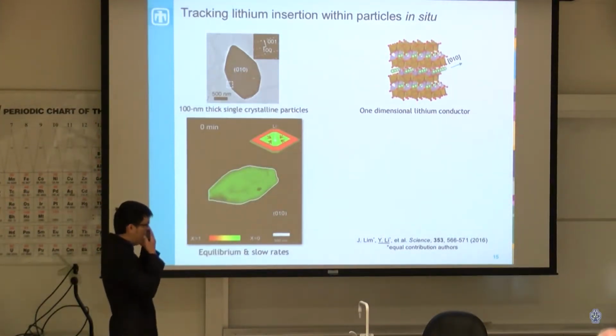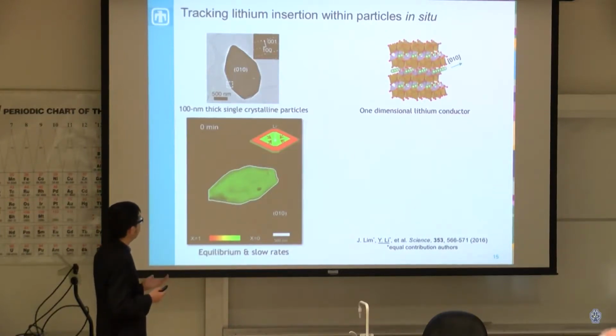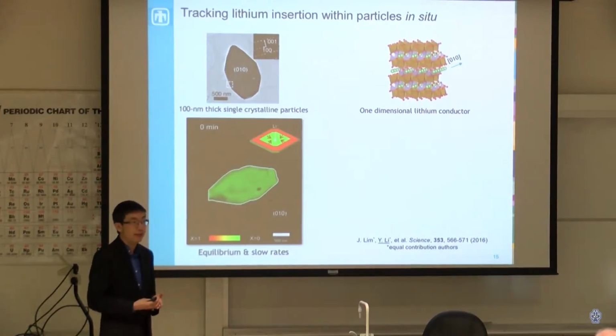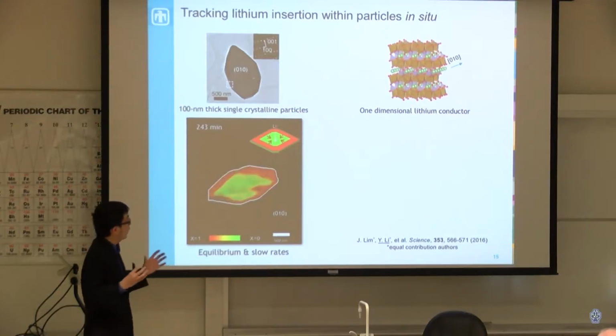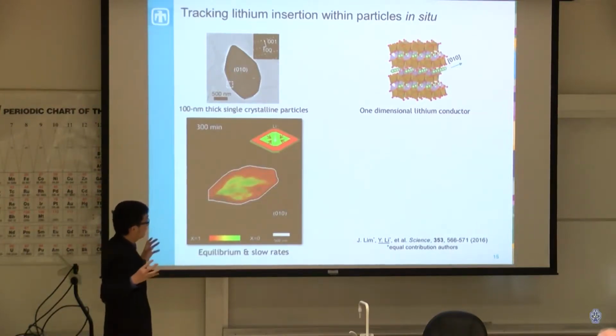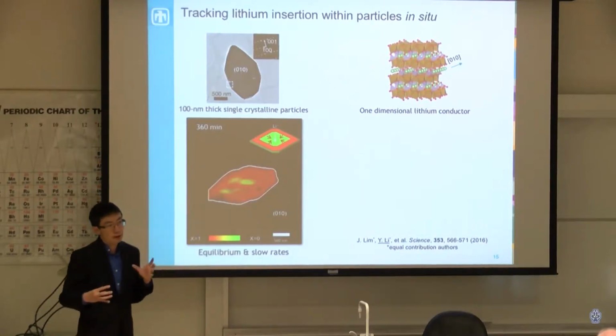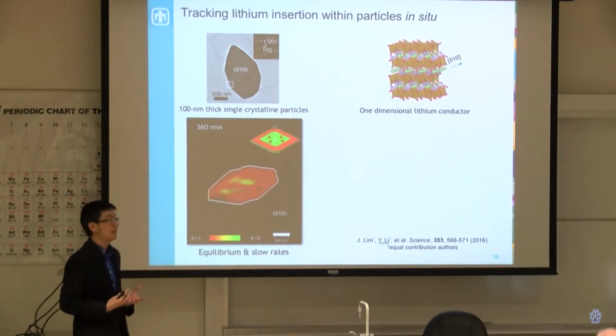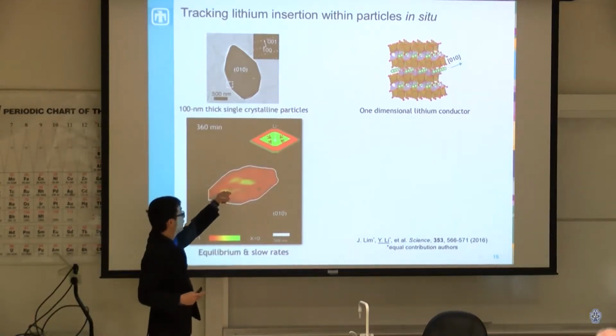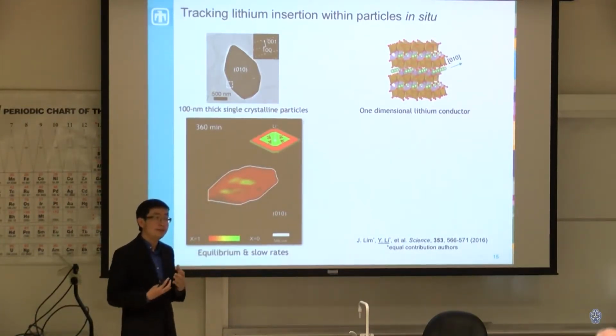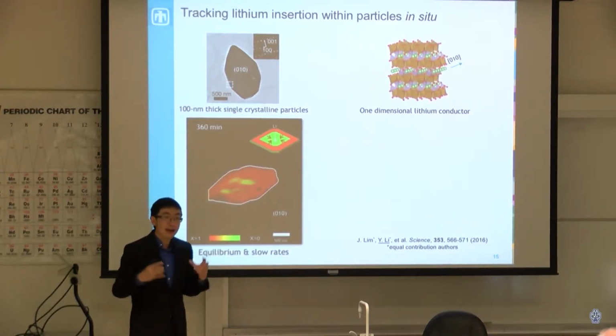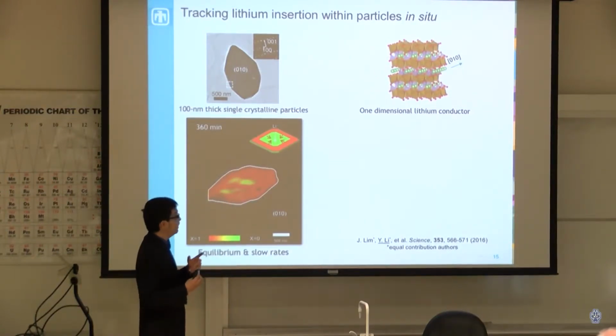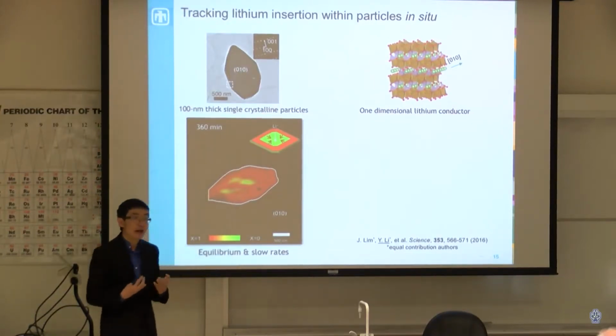So if we look at what happens when we do the imaging, this is one particle that we image when we put lithium into the particle. The green means that that region is devoid of lithium, whereas red means the region has a lot of lithium. What we can see is that the lithium likes to aggregate near other lithium. So lithium insertion starts from the outside and seems to go inward. Normally we might think of this as just a diffusional process, but it's not quite so, because lithium diffuses into the page and not from the outside in. So what's happening is that when you put lithium into this particle, it likes to be near other lithium. Lithium is attracted to other parts of the particle that also have lithium.